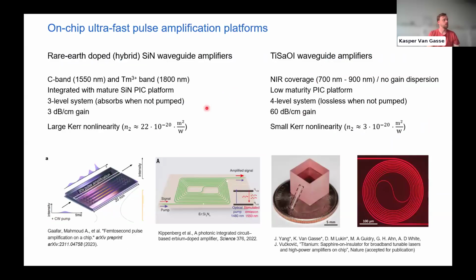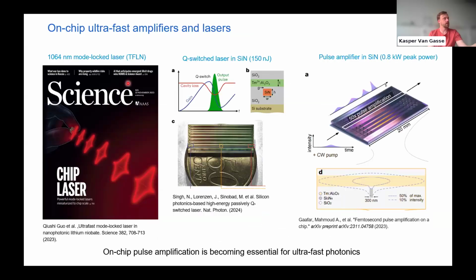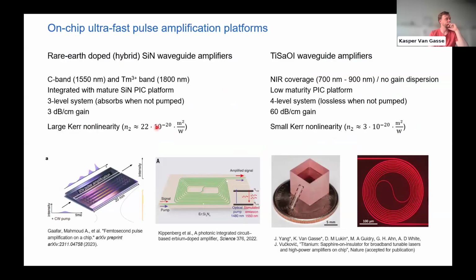All right, so what is now holding us back and what can we improve is that all the ultra-fast optics, or most of it, was done using rare earths in combination with silicon nitride. And that has some drawbacks. It has a lot of advantages. It's wafer scale. You can implant it. But it also has a few drawbacks. One of them is it's a 3-level system, so it absorbs when it's not pumped. That also means that you need very careful pump management in these integrated systems.